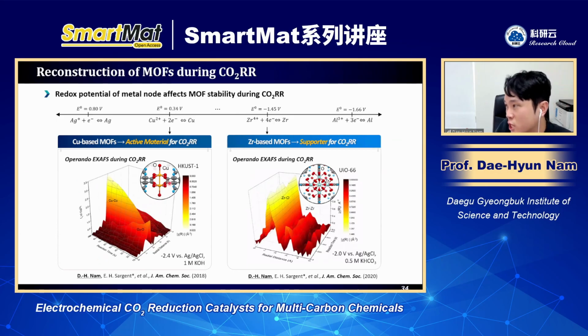In this way, the MOF structure will be changed. The copper contributes to maintaining the porous structure, but this copper is being reduced to fabricate nanoparticles or clusters. But in the case of zirconium, as I show, there is no change in the coordination number of zirconium. It means although the reaction starts, the zirconium number does not increase, and we can see a lot of zirconium-oxygen bonds here. It means the zirconium does not participate in reconstruction. So we need a different point of view to understand the MOF. The copper-based MOF can be applied as an active material, but the zirconium-based MOF can be applied as a support because it is very stable.